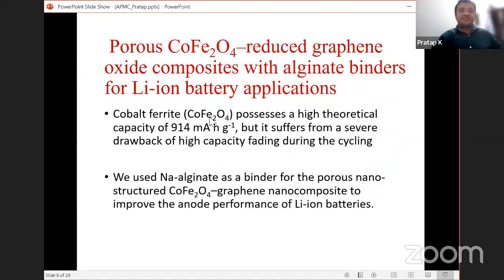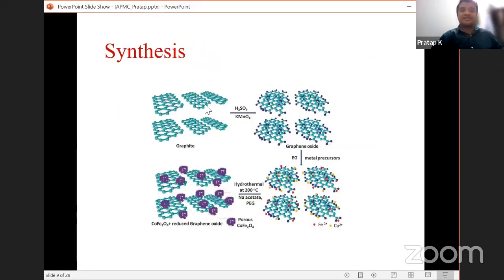Now, this is cobalt ferrite. Cobalt ferrite possesses a high theoretical capacity, 914 mAh per gram, but it suffers from capacity fading. So we thought we could add a binder. We added a sodium alginate binder into this porous structure, and we want to enhance the performance of lithium ion batteries. So this is the synthesis method.